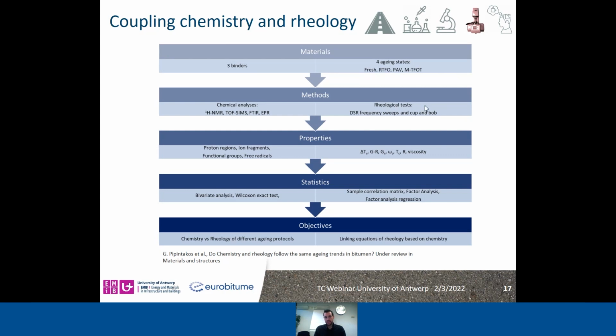And also rheological testing, typical frequency sweeps with dynamic shear rheometer and viscosity tests that were performed with cup and bob. And after constructing master curves, different rheological parameters, indicators, which are not standardized ones, but they are more meaningful in terms of distress types according to literature, were used. I will go through them in short in a next slide.